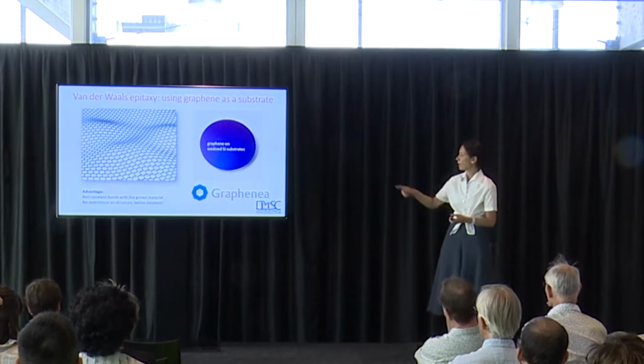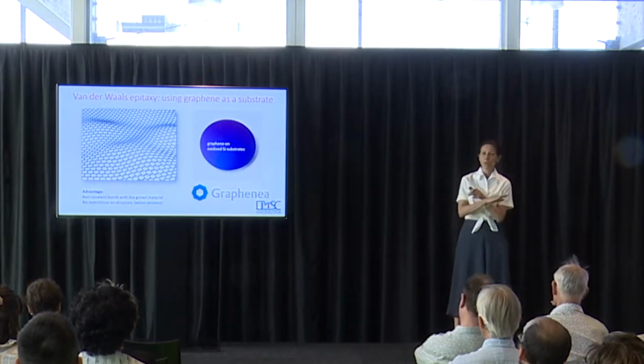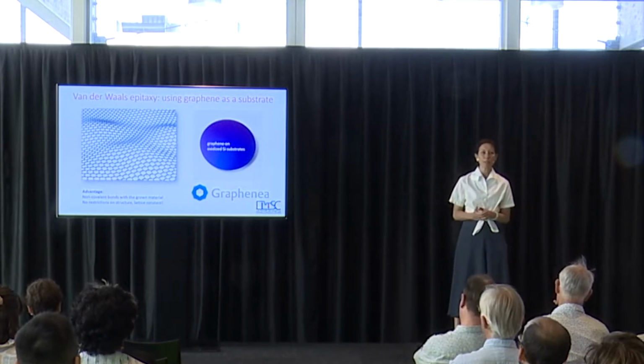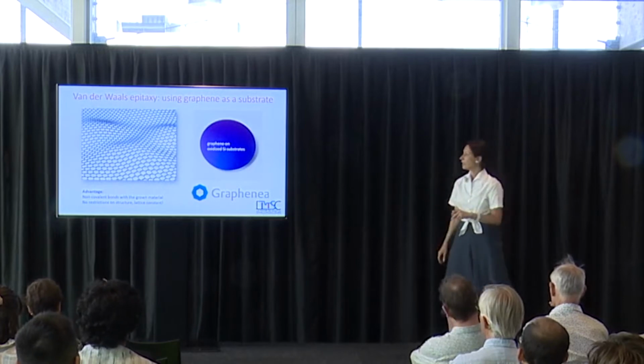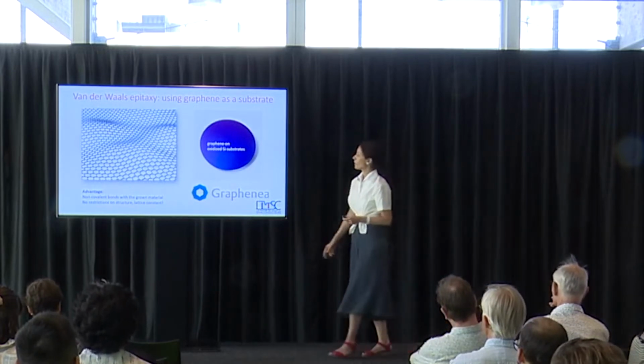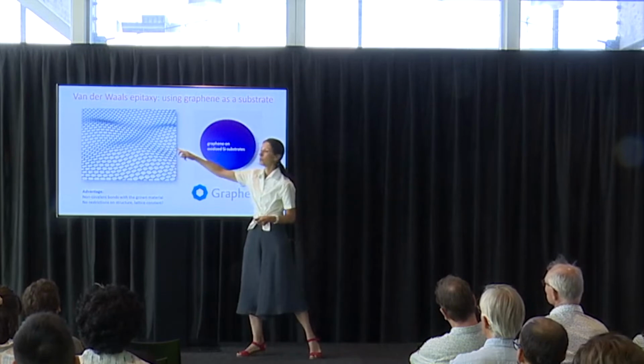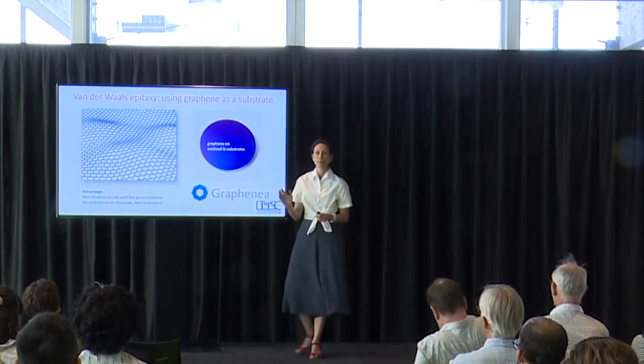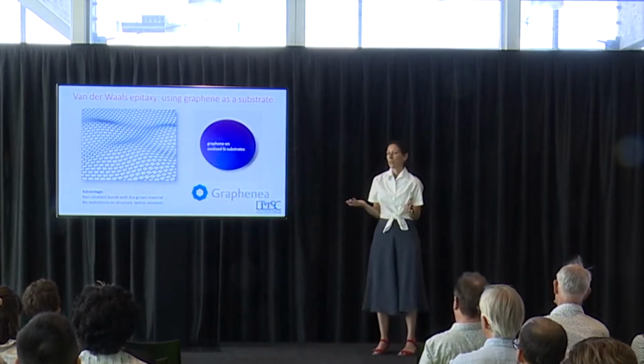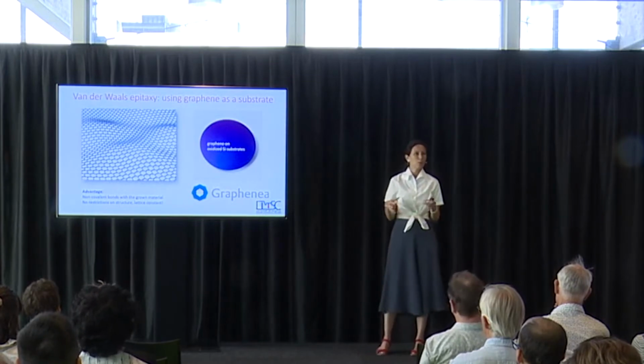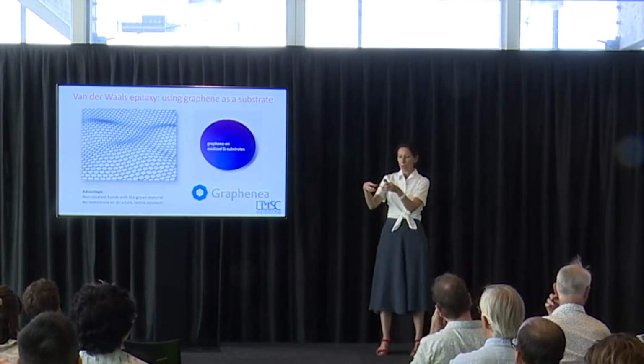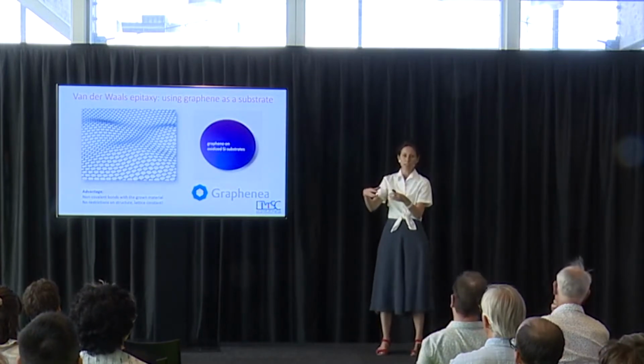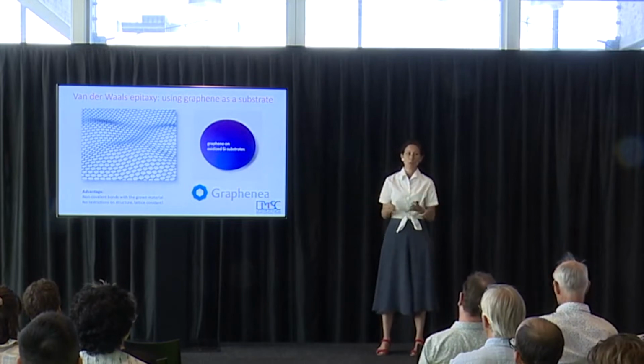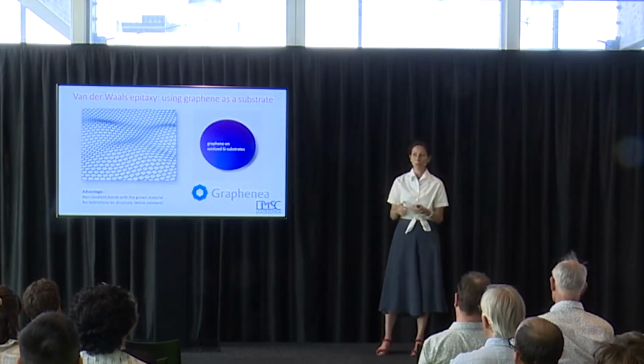If you would have a full wafer like this with a full monocrystalline layer of graphene, and you would evaporate your material, because there is no covalent bond, the material would arrive here, it will wander around and dissolve. So nothing will happen. It may eventually happen if two atoms meet each other and then they would start creating an island, but nothing would happen. So it would grow for a long time and nothing would happen on your substrate.